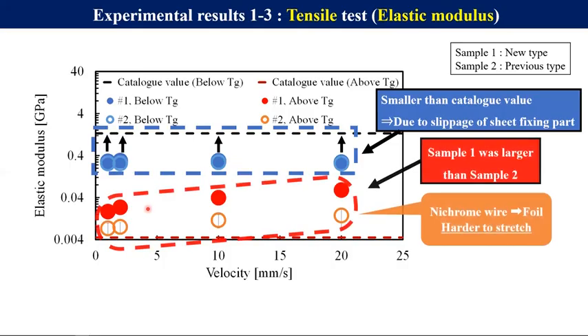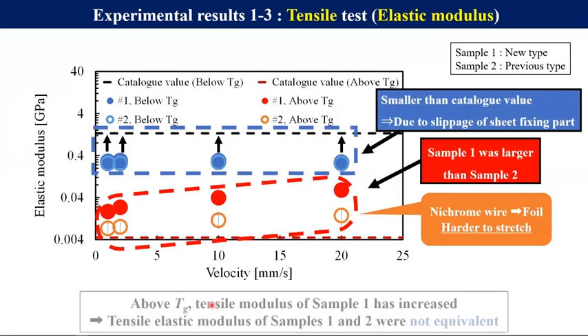However, when it comes to the tensile elastic modulus above TG, it can be seen that the tensile elastic modulus of sample 1 was obviously larger than sample 2, and we assume that this is due to the change from nichrome wire to foil, which increases the longitudinal modulus of elasticity and makes it more difficult to stretch. So based on this result, we found that the tensile elastic modulus of samples 1 and 2 were not equivalent.